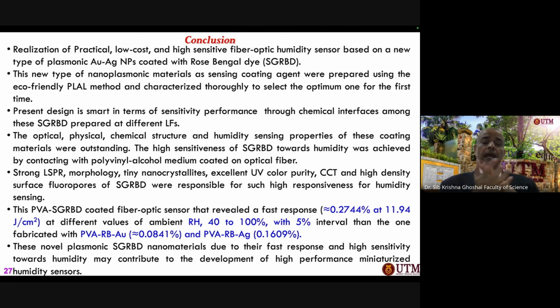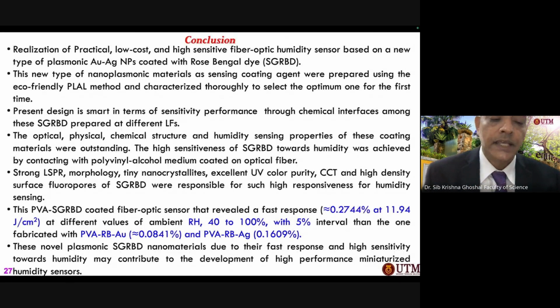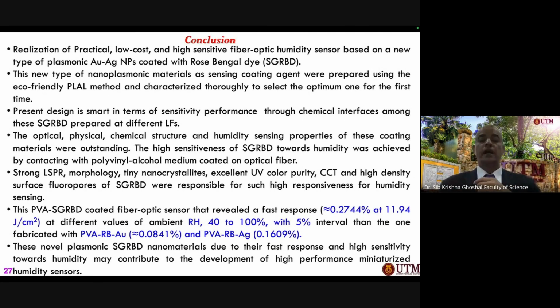And we can really get very high sensing performance using rose Bengal dye in combination with a polyvinyl alcohol layer. As I told you, the more ligands and surface passivated states you can create, the better the humidity sensing would be. It's all about the surface chemistry. It's all about the surface reactivity, where electronic densities of states and optical densities of states play the important role. That's the fundamental physics, that's the fundamental science we must understand.